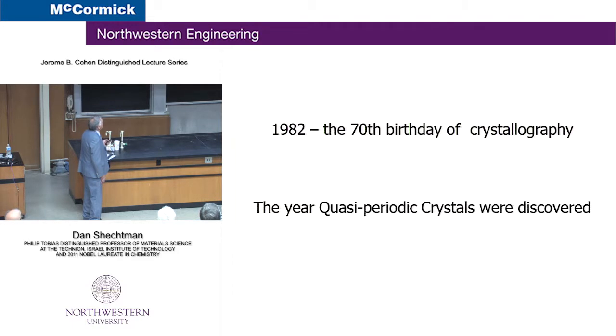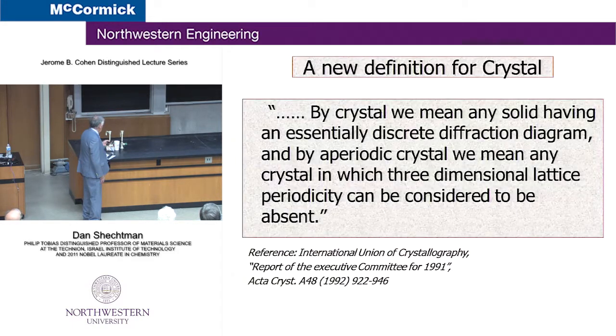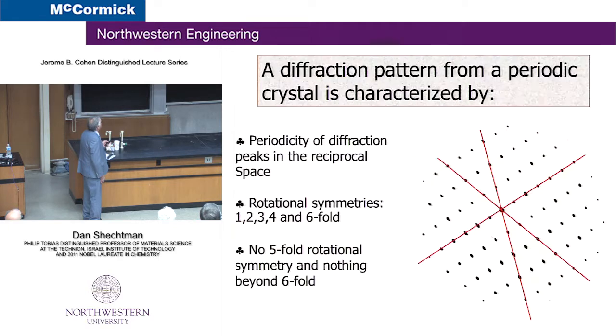And you see, too fast, too fast. Come back, come back. Okay. So you see periodicity in this direction, and periodicity in this direction, and periodicity in this direction. So you take any distance between the central spot and one diffracted spot, you multiply it by any integer, say 2, you see that there is another spot. Distance from here to here, multiplied by 2, you're here. Multiplied by 3, you're here.